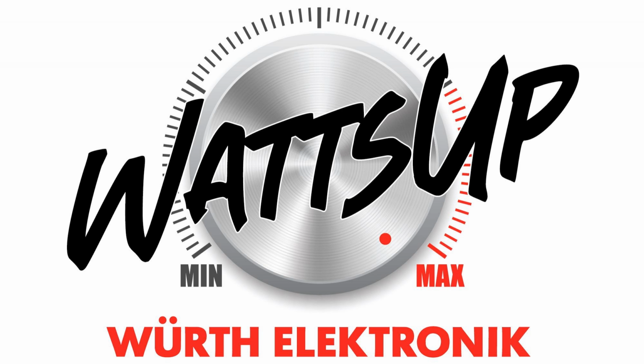Coils having ferrite core materials show a variable inductive behavior with change in the ambient temperature. There are two important concepts to take into consideration. On one hand, the maximum operating temperature range, and on the other hand, the Curie temperature. It is highly recommended that the temperature of the component does not exceed this maximum operating temperature under worst case conditions. This range is dependent on the core material chemical formula.